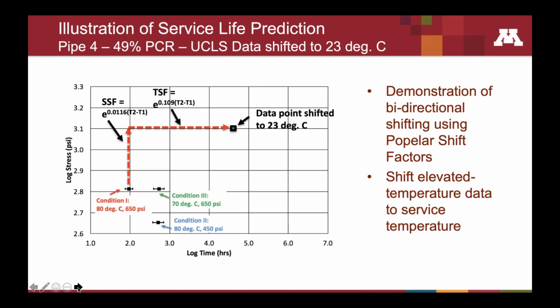In Minnesota, where I live, we're going to be shifting that even further to the right because it's going to be much, much cooler than 23 degrees in an in-ground condition. We can do that same shifting for the other 2 data points. And what we get is what we call a master curve. And that master curve is that same slope as that brittle curve that I showed you, those stage 2 curves that I showed you from earlier before.